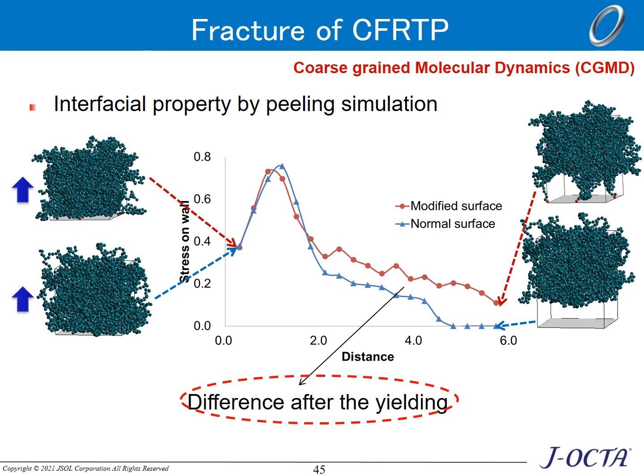The polymer was set up as a glassy state and peel-off calculations were performed. The graph shows the stress characteristics. There is no difference in the elastic region and the yield point in the two cases, and there is a difference in the fracture region. This is the same tendency as that of the cohesive element on the previous page, so this demonstrates the validity of the parameters we set.